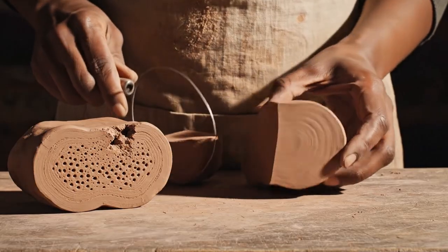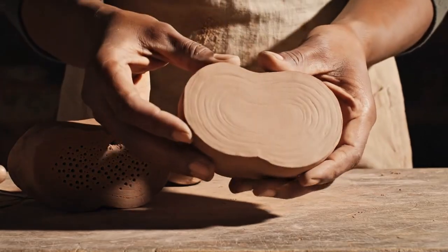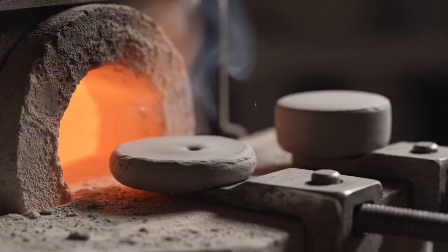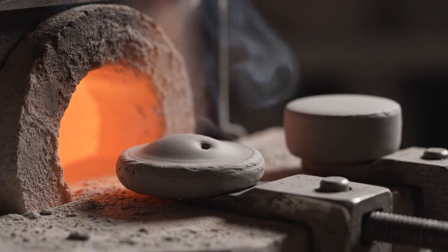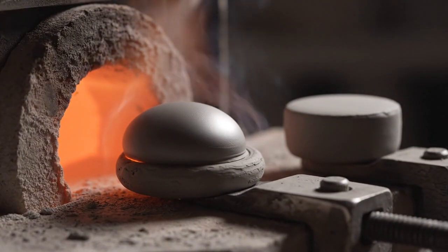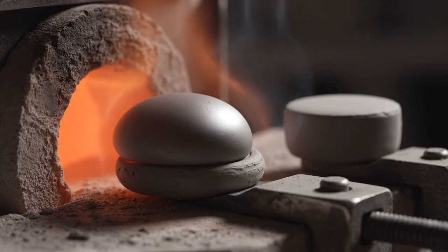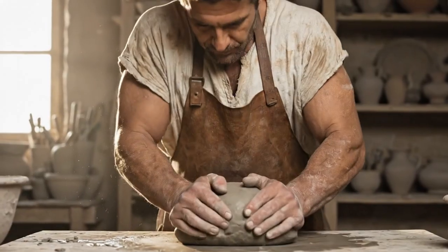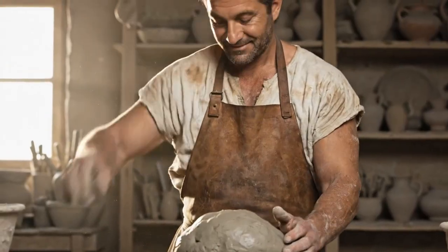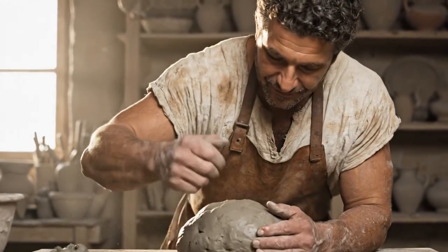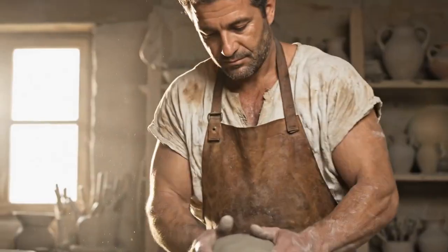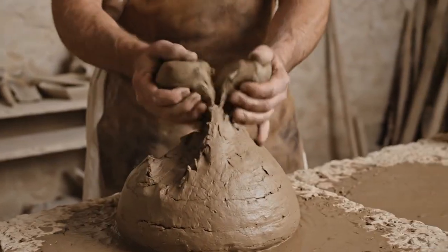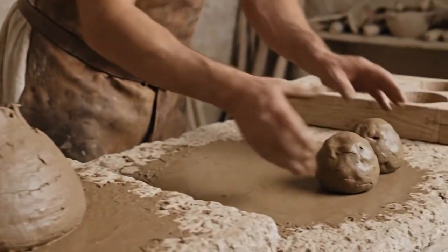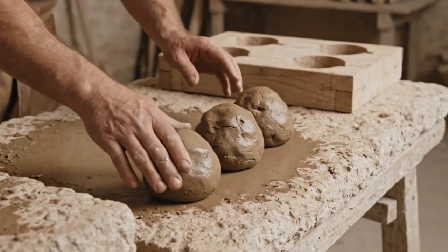An air bubble left inside the clay body is a death sentence in the kiln. As the temperature rises, the trapped air expands, and the pocket becomes a blister, or worse, a violent rupture that destroys the lamp and potentially damages its neighbors in the kiln stack. The potter works for 10 or 15 minutes until the clay is completely homogeneous, pliant, and cool to the touch.